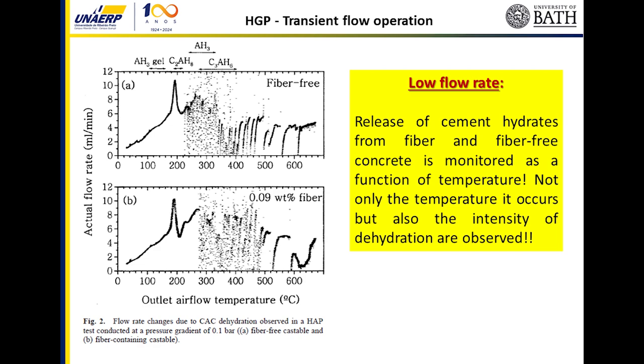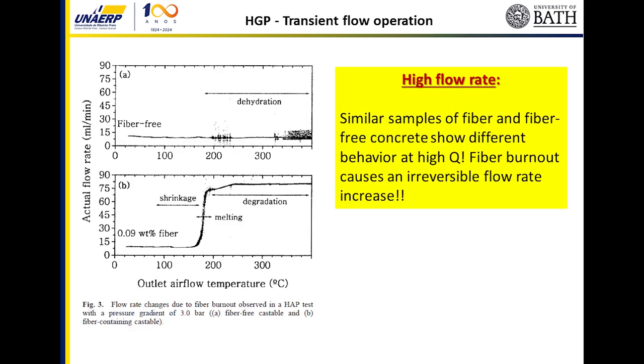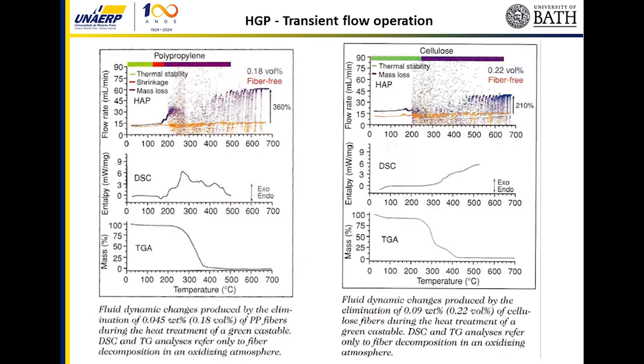But if you take the same material and do it with a higher pressure, you can see exactly the temperature that the fiber goes out, and you have the increase in permeability, because the fiber normally is used in concrete to increase the permeability, the refractory concretes. You put the fiber to create voids. Why? Because when you create voids, you make easier the drying of the concrete. So this is another technique that you have.